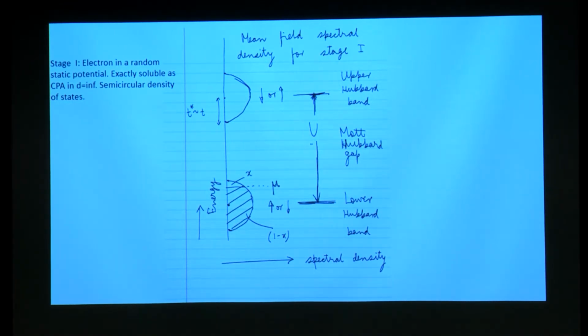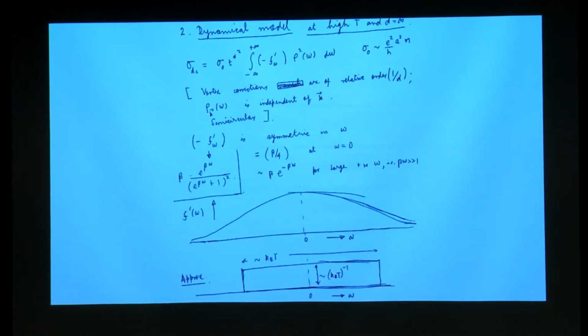So this describes a system with, you see, this is the single particle density of states. It has no peak, so there are no quasi-particles. But because of strong correlations, there is a lower Hubbard band and an upper Hubbard band. All this is known in some form or the other, very well known. Okay. All right, so I use this model, which I believe is appropriate for a strongly correlated system at high